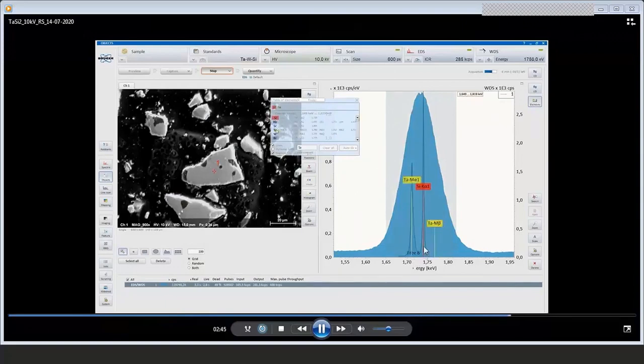So there's silicon indicated in red, and there's tantalum indicated here in yellow. We expect here a second line for tantalum. This should be the tantalum M beta line. And actually we see here the increase of the impulses, so the increase of the count, so the tantalum M beta line is actually there. So this is how we capture a range scan. And you see in the background, this is the EDS spectrum section, and here's the WDS range scan. We are always acquiring at the same time.